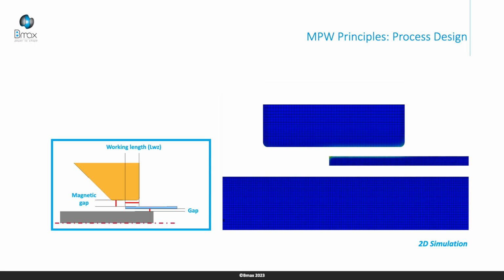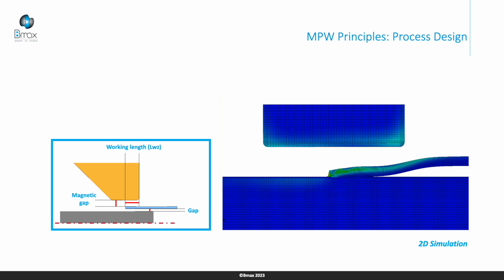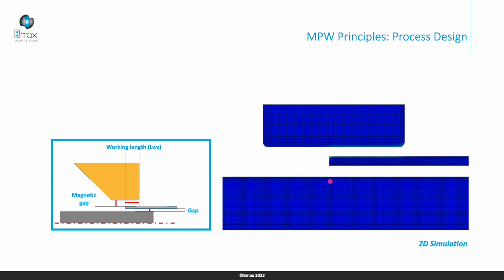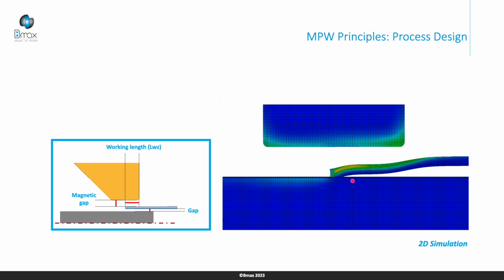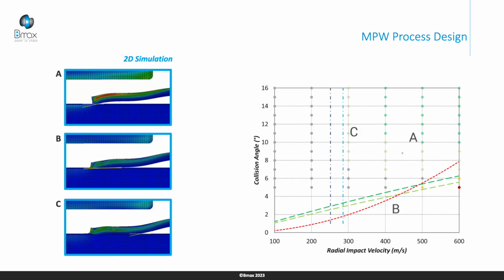After, in terms of simulation, we perform 2D simulations. You can identify the 3 critical parameters: the working length, the magnetic gap, and the gap between the workpieces. During the simulation, we can track for each node at the interface the angle and the speed. This way, we are able to project this data on the welding window, and we can analyze what happened during the process as a function of these 3 parameters: working length, magnetic gap, and the gap.